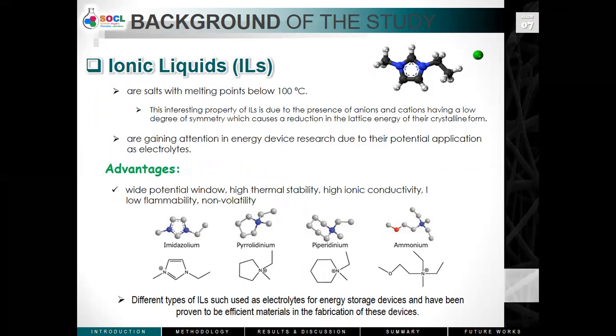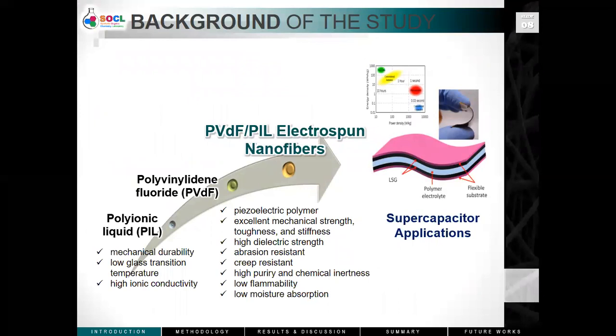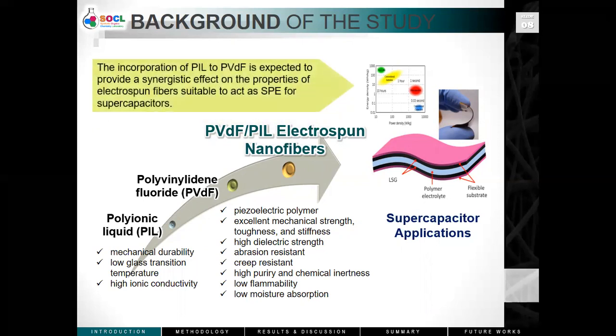Certain ILs, depending on the structure of their alkyl group, can be polymerized, making them amenable for blending with other polymers. Polyionic liquid offers mechanical durability, low glass transition temperature, and high ionic conductivity even in the absence of organic solvents, thus making them appropriate to undergo electrospinning. On the other hand, polyvinylidene fluoride, or PVDF, is known to be a piezoelectric polymer that has been used in several applications due to its mechanical integrity. The incorporation of PIL to PVDF is expected to provide a synergistic effect on the properties of electrospun fibers, suitable to act as solid polymer electrolyte for supercapacitors.